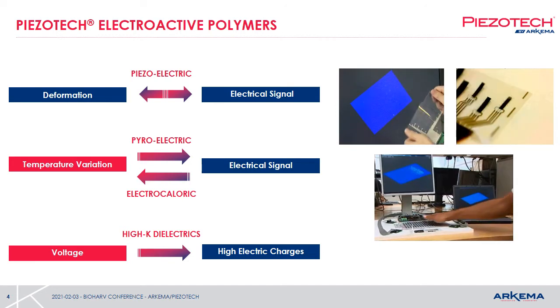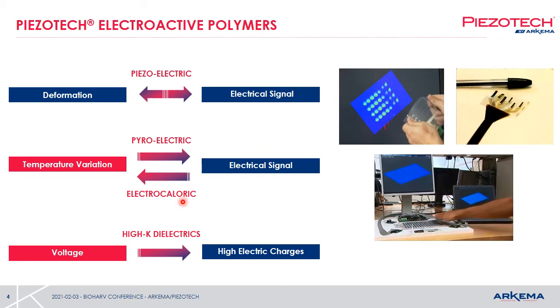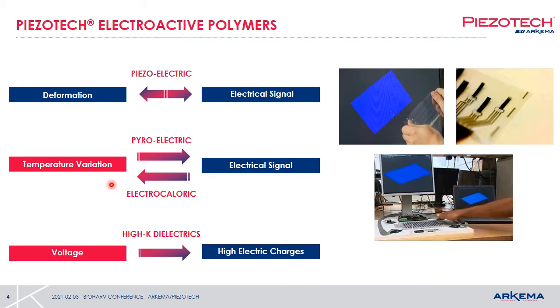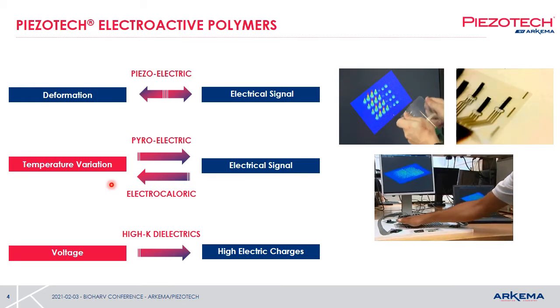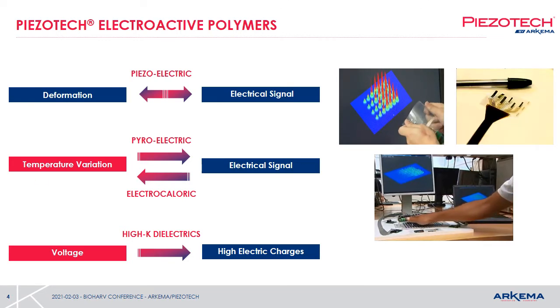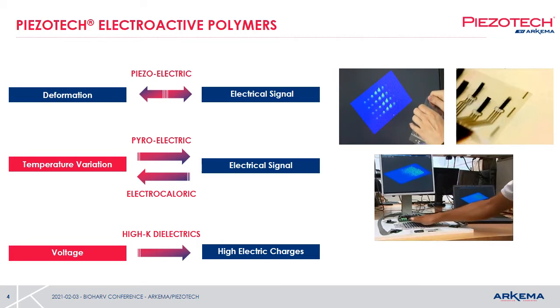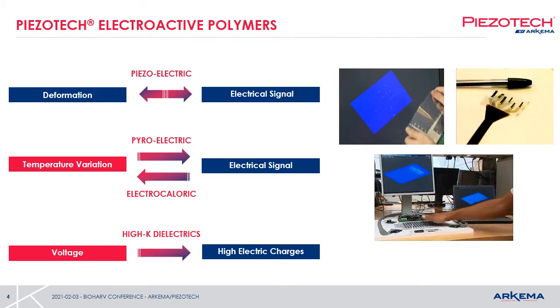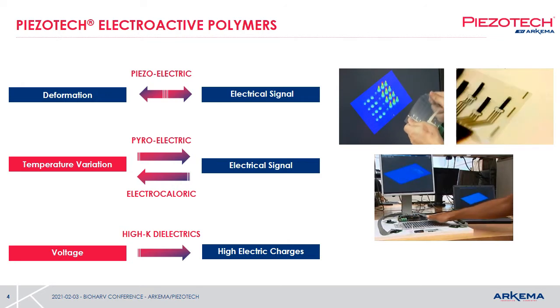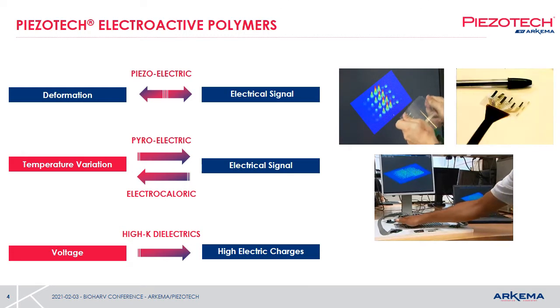A pseudo-reverse effect, not really the reverse one, is the electrocaloric effect. When you apply an electric field, you're going to create an entropy variation in the material that is going to generate temperature variations. And also, in the beginning of the 21st century, the terpolymers were developed, especially in the US, for their high dielectric permittivity properties, what are called high K properties, especially in order to develop high performance capacitors. And now these properties are still of very high interest, for example, for thin film transistors.